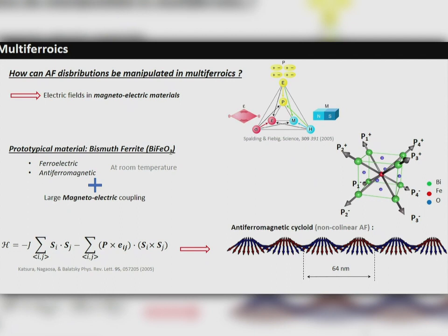So coming back to bismuth ferrite, which we can call BFO, it has this kind of perovskite structure, with the ferroelectric polarization, which can lie along the 1-1-1 directions. And we have to mention that there is a quite large magneto-electric coupling, and the first consequence of this very large magneto-electric coupling is what we call the antiferromagnetic cycloid. So it's an antiferromagnet, but then it wants to curl and to wind in a chiral way, and this is because of this magneto-electric coupling.